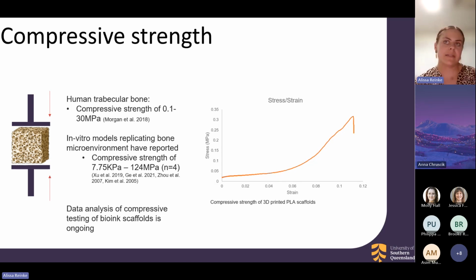Now, keeping in mind, there are only 4 papers that have actually reported on the compressive strength of their scaffolds. So there are other papers and other groups doing this, but only 4 have actually reported on the compressive strength. Now, a lot of the current 3D models being used are printed through plastic, whether it's PLA or PCL. I have also created some plastic scaffolds just as a comparison, and the compressive strength of those was found to be between 0.3 and 0.35 MPa, which is within that range of human trabecular bone.